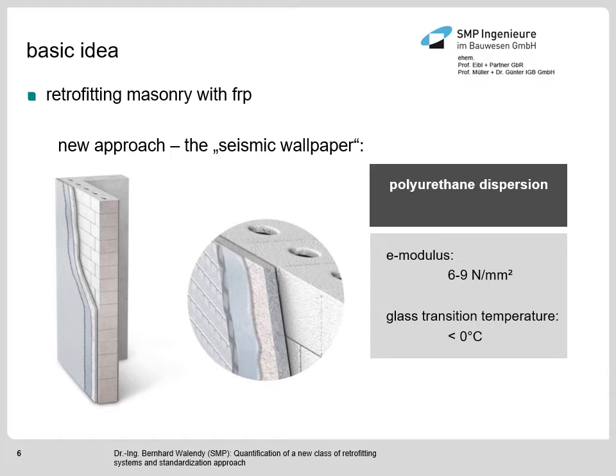Also quite an important point to mention is that the glass transition temperature is below 0 degrees Celsius. And this is really distinguishing from epoxy systems, which have glass transition temperatures of something between 50 and 80 degrees Celsius. So this glue is used above its glass transition temperature, and this is the main feature of the system. And I want to show you why these special material properties of the glue are so important to the system.